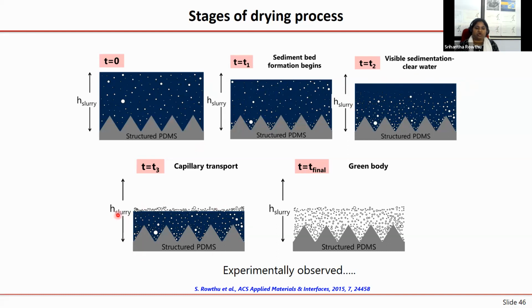And then finally, on the top surface, it just felt like it had completely dried. Now, at this point, because I did not know that there was still liquid, I tried to demold and found out that inside there is still quite some liquid because it is still evaporating. Okay. So this is an intermediate stage, and you have to leave a sufficient amount of time so that all the liquid firstly comes up through the capillarity process and then undergoes evaporation. Here it's direct evaporation and permeation. Here permeation is continuing, but for evaporation, it has to first undergo a capillary process. Then finally what you get is a green body after you demold this material from the PDMS. These all phases are experimentally observed.